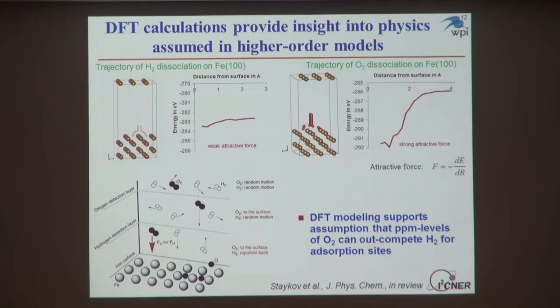And so what he did was a series of potential energy scans for hydrogen approaching an iron surface and oxygen approaching an iron surface. And I'm not going to go through all the details because I'm running out of time, but what Alex came up with was basically this schematic which depicts his findings, and that is at a certain distance away from the iron surface, both oxygen and hydrogen would just be moving in random directions. But as we start to approach that iron surface, the oxygen is going to sense the surface first. And so this oxygen is going to start to be drawn towards the iron surface at a distance that's further away compared to the hydrogen.